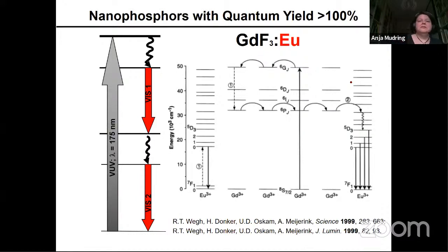And those materials are known. Again, we stay with the rare earth. Praseodymium alone can absorb UV light and send out 2 red photons. The process is not very efficient, but you can use a combination of 2 rare earth ions, and that's gadolinium and europium. So you take gadolinium fluoride and you dope it with europium, and then you can excite the gadolinium, which is the host material. So you only need about 1% of europium in the host lattice.